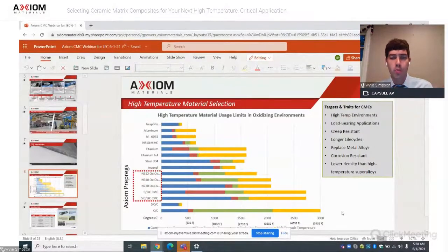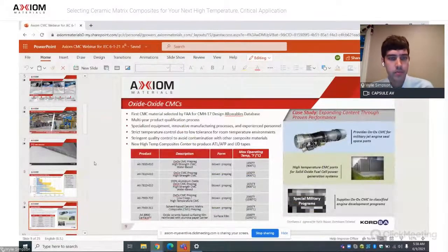But we do sort of the more common and the more successful version of that, which would be to reinforce that monolithic with fibers. Ceramic fibers specifically, to bridge those cracks, to deflect them, to impede their movement through the ceramic material, and that's what we do. So there's a few different versions of the CMC prepreg that we have to offer that I'll talk through later or right now. So we have a few different systems that vary on the matrix as well as the fiber, and these are all tailored sort of to your max operating temperature, as well as the structural properties that you're looking for.